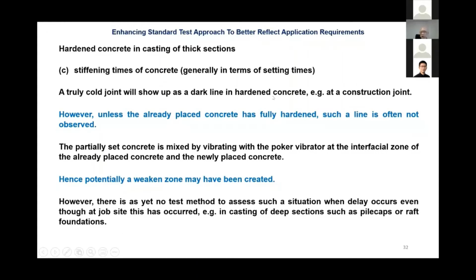Now, a real cold joint is a construction joint, and you can always see a black line. However, in our actual practice, we don't always end up with a definite cold joint. What we have in practice is new concrete placed over the delayed concrete and mixed in with a vibrator, which they always do on the job site. No matter how long the delay, the subcontractor will never stop work because he has ordered all the concrete and he has to finish the job. Otherwise, he doesn't even know how to restart. So we always end up with a big issue on the job site.